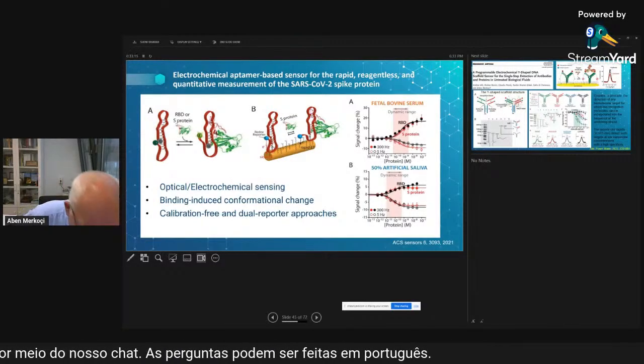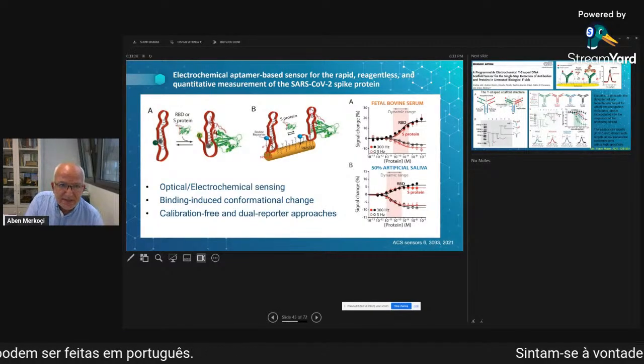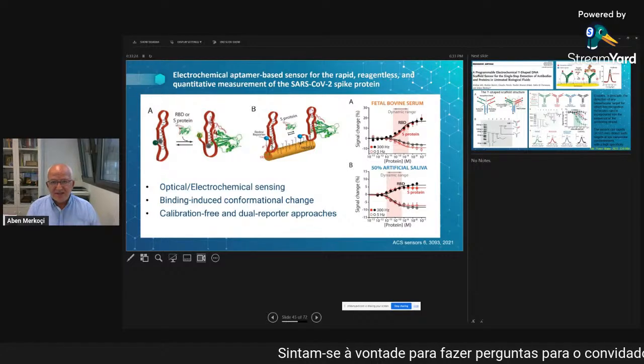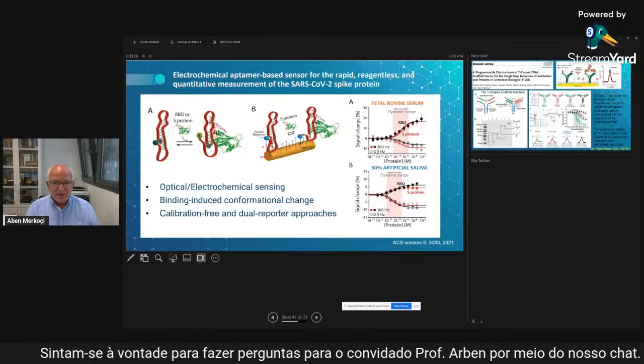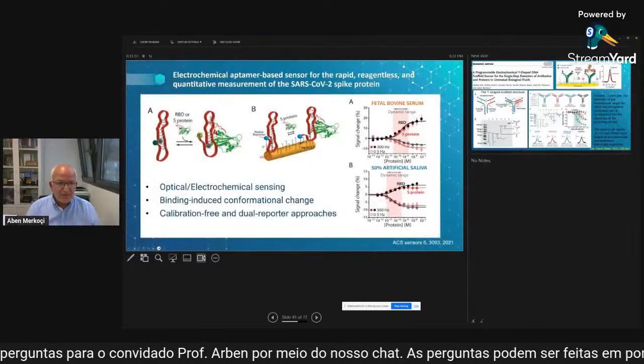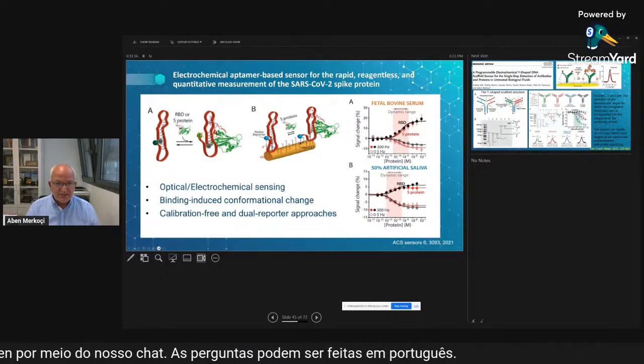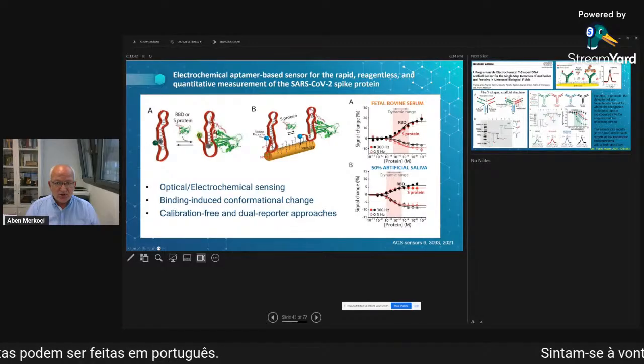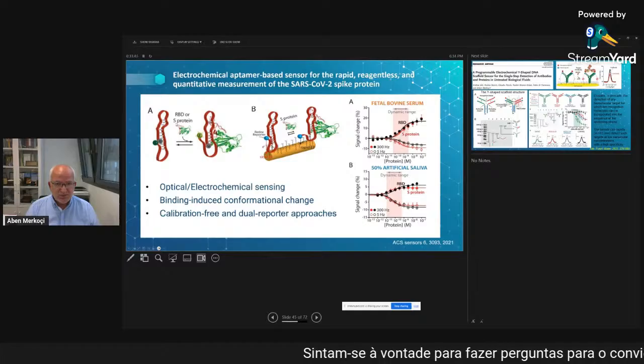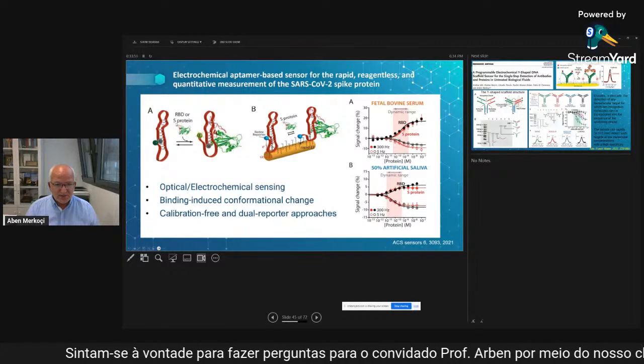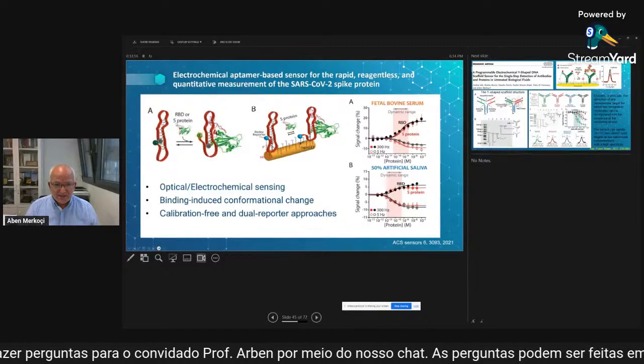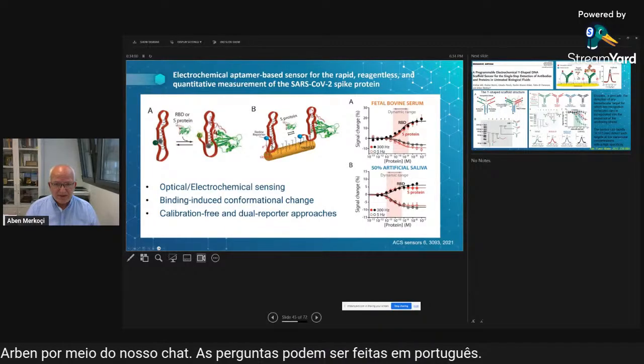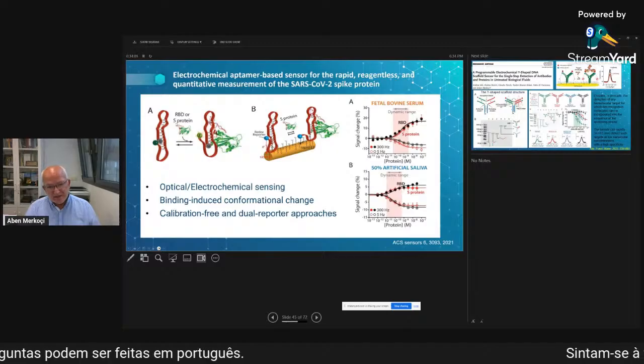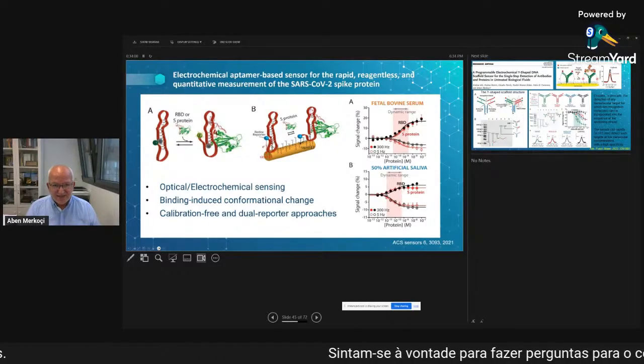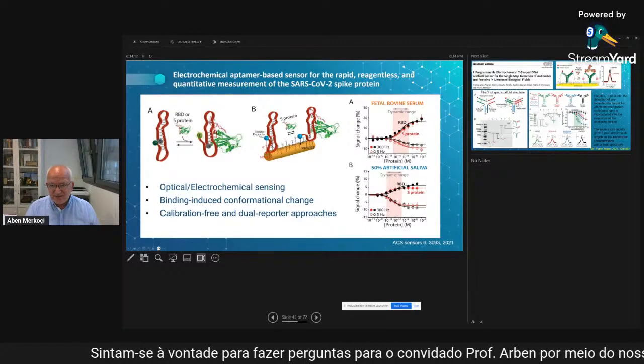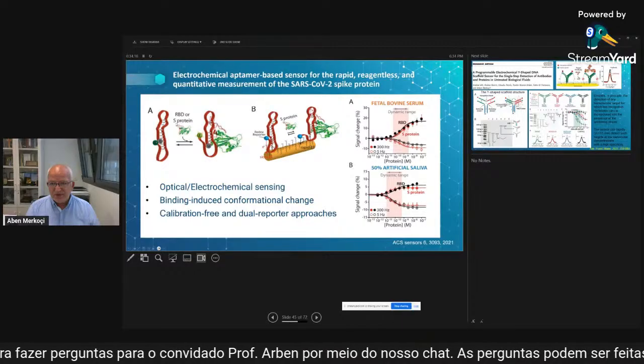We also moved toward very sensitive detection of some proteins, and in this case you see the aptamer-based sensor for the rapid and reagentless, quantitative detection of SARS-CoV-2 spike protein. You see this is a very, very interesting system in which we have a gold nanowire that is modified with an aptamer against SARS-CoV-2 spike protein that interacts specifically with this protein. This aptamer is connected with a redox reporter, methylene blue, that you can see. Upon interaction with the SARS-CoV-2 spike protein, the distance of the redox reporter to the electrode, in this case the gold wire, is changing, so the transfer of electrons is changing, and we see the change of the current signals versus the concentration of this protein.